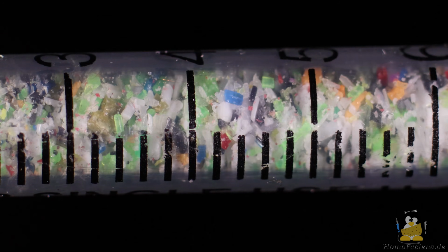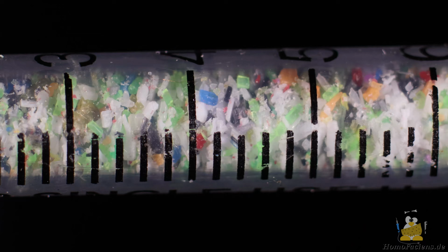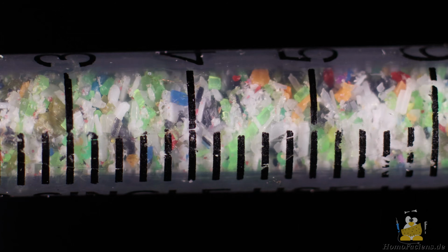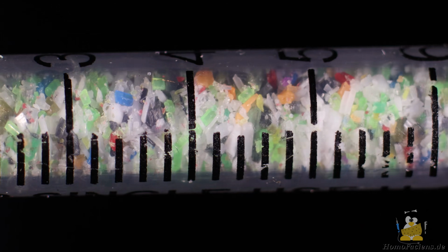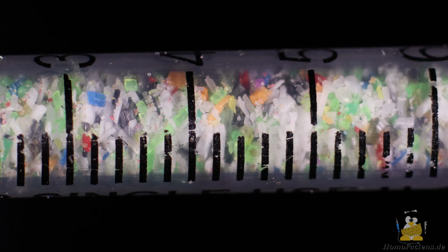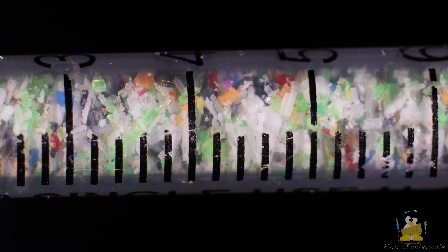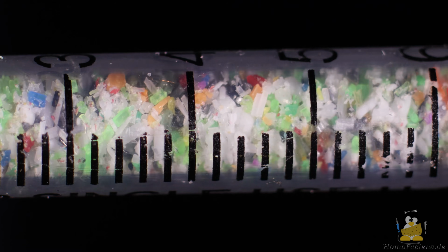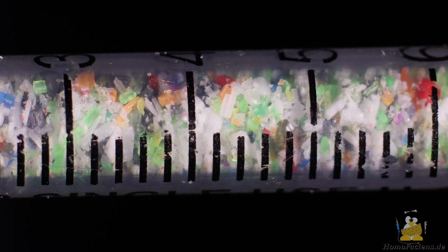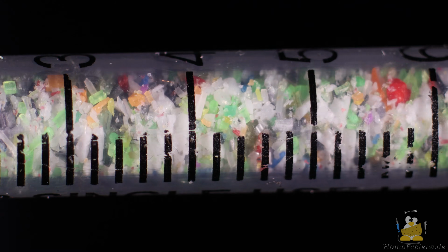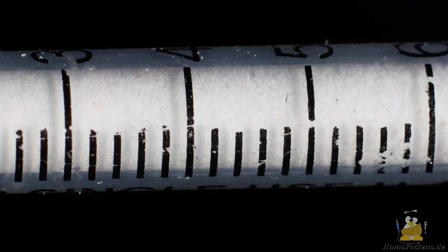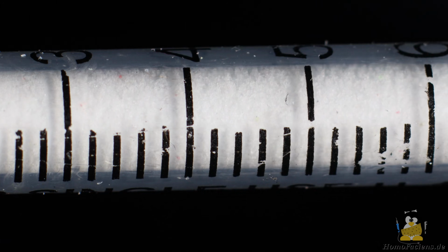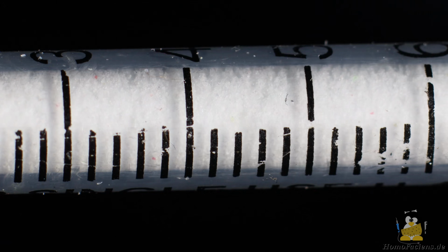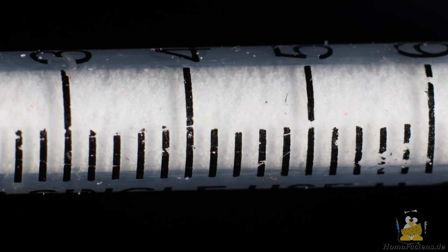The recycled powder consists entirely of sharp-edged grains, however these are smaller. Consequently, if a single grain snags, it does not block the entire tube. As demonstrated, the powder is compressible, allowing a snagged grain to shift inward and immediately break free from the wall. The material moves through the tube much more uniformly. Material transport is smoothest with industrial powder, it effectively flows through the tube.